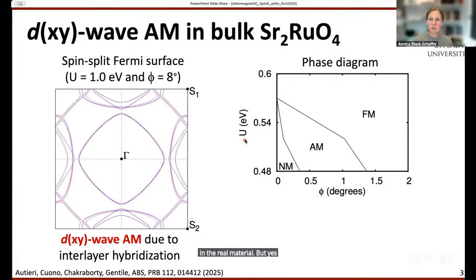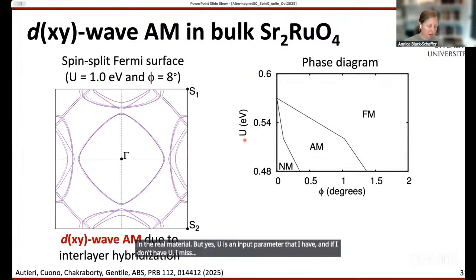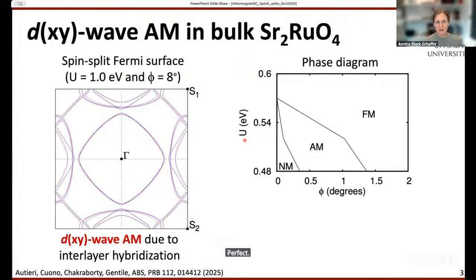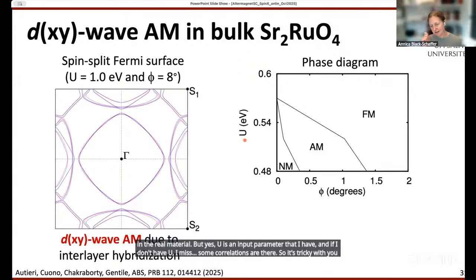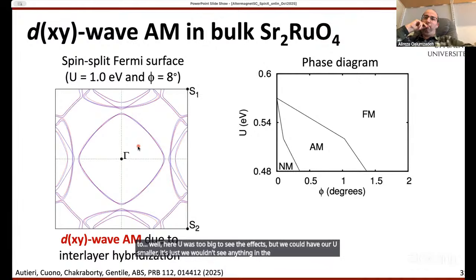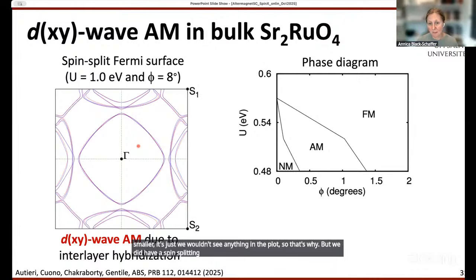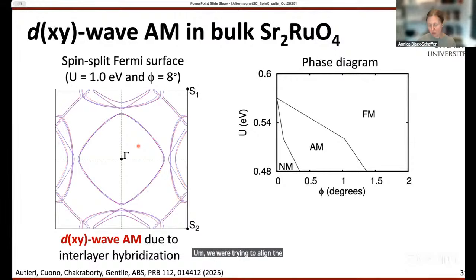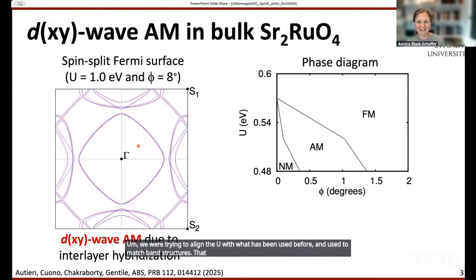But yes, U is an input parameter. If I don't have U, I miss some of the correlations that are there. So it's tricky which U to pick, and it's not a first-principles U; I have to choose it and then try to match it as well as I can. Here U was too big to see the effects, but we could have a smaller U. It's just that we wouldn't see anything in the plot, which is why. But we did have the spin splitting. We were trying to align U with what has been used before to match band structures. That is as much as I can say. Yeah, thank you very much.